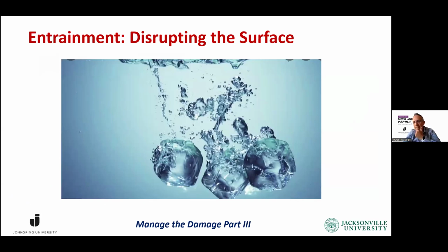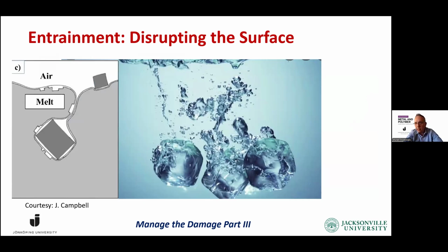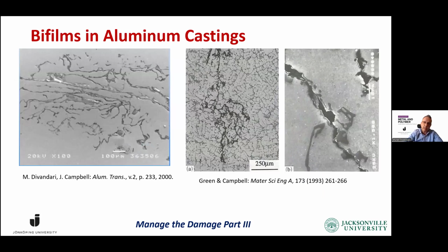So when we don't like the temperature of our water, what we do is we put ice in it. There's no problem with it because the surface of ice is still covered with water. But if we put ingots in liquid aluminum, we again create damage. The surface of the ingot is also covered by a thick alpha oxide. So we keep on giving damage to the liquid aluminum as we disrupt the surface. And that all comes from the fact that we treat liquid aluminum as if it were water. So the result is bifilms in aluminum castings.